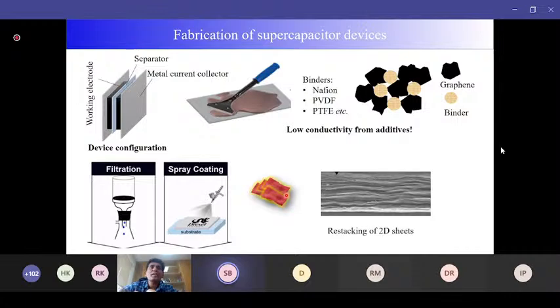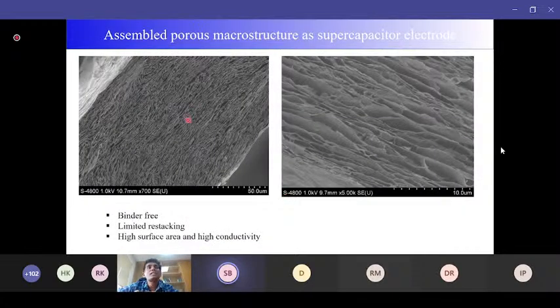So in this case, what could be the best possible scenario? The best possible scenario could be this one. You assemble the nanomaterials in a form that is some freestanding structure, having no additives of the insulating polymer, but it is not very compact, having some porous structures. These are some porous structures. This is the high magnified image. You can see that there are a lot of pores, and these are the sheets of graphene here. In this case, because there are no additives, the conductivity will be higher, and because there are a lot of pores, the interior of the material can be accessed by the electrolyte ions. So this is the target to achieve.